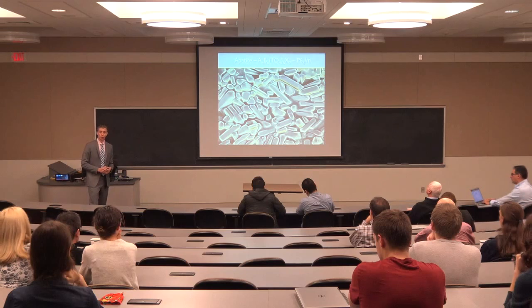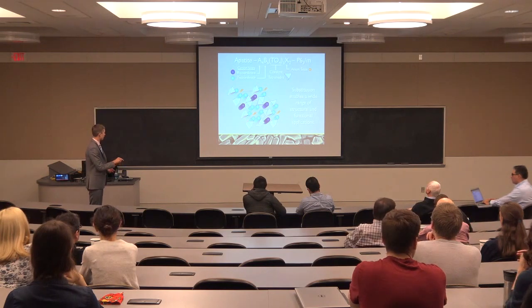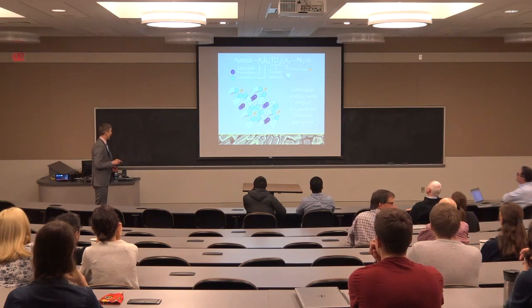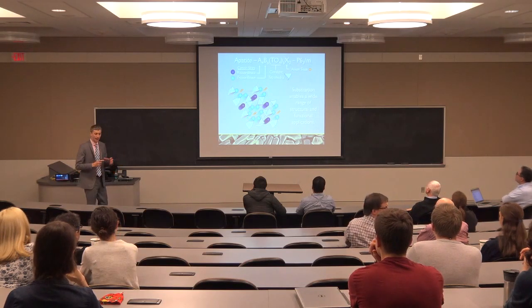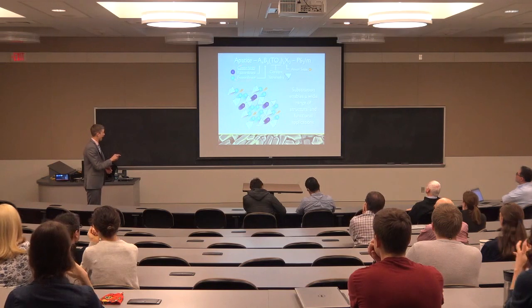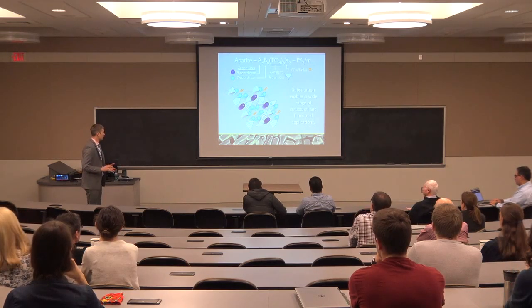The hexagonal crystal structure is represented by this general formula shown here. The structure is made up of these covalent tetrahedra, and the arrangement of those tetrahedra produces two distinct cation sites, one 7-coordinate and one 9-coordinate, that are arranged as columns along the c-axis of the unit cell. There are also these anion sites located in the center of this ring of cation sites, and we can put a variety of atoms into these different sites, different sorts of tetrahedra, different cations, leave some of these empty, fill them up, and based on how we change the population of sites in the crystal structure, we can enable a wide range of potential applications.